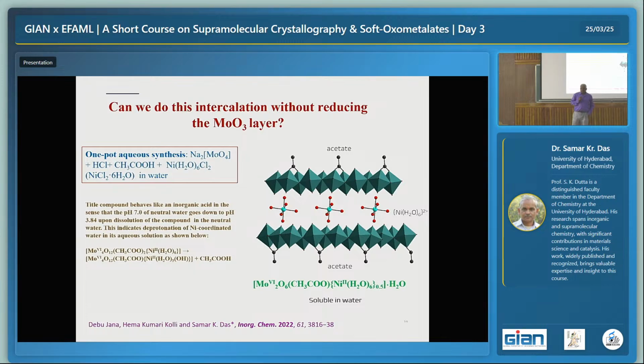Not only that, if you dissolve the compound in water, the pH becomes 3.8. Water is pH 7, no? The pH becomes 3.8. That means the compound is an inorganic acid, isn't it? Why is it happening? Definitely, when you dissolve it, some proton comes out. If a proton has to come out, what is the possible thing? Definitely some deprotonation of the water. With inorganic chemists, we did acid-base titration, and we found that one of the waters actually gets deprotonated and it formed like that. So in the solution, you get nickel pentaaqua hydroxo. This compound formed, and that's why it is acidic in nature.